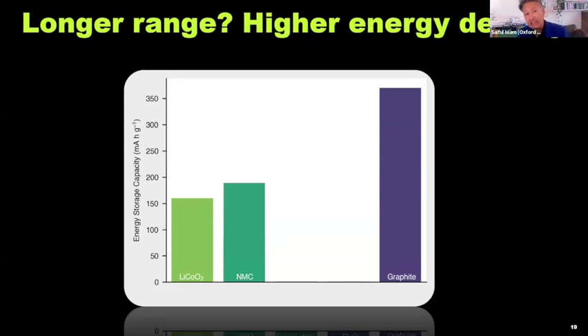So what I'm showing you here is the energy storage capacity along the y-axis. Don't worry about the units, it's just basically a relative plot. Along the x-axis, I'm showing you some different materials. The light green on the left is lithium cobalt oxide. The darker green is NMC, which is a layered nickel manganese cobalt material. And on the right, in purple, is the negative electrode, the graphite. And even if you're not a battery chemist, you can see there's a big difference between the energy storage of the cathode and the graphite. So we need to increase the energy density of the cathode.